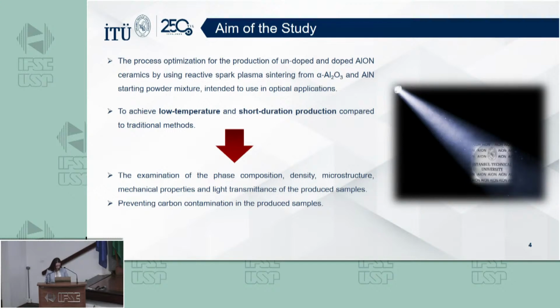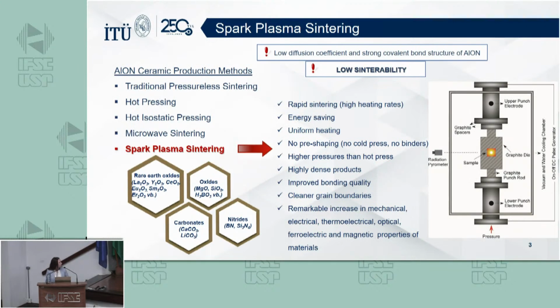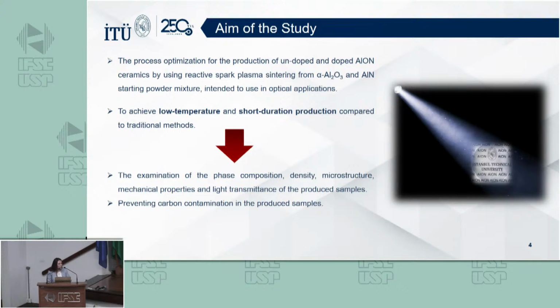And AlON production is an energy-consuming process, so spark plasma sintering is an effective way to get highly dense and transparent AlON ceramics in a shorter time and lower sintering temperature. But the main challenge is the carbon contamination due to the graphite equipment in the SPS system. So we have a recent publication about the prevention of the carbon contamination of the produced AlON samples.